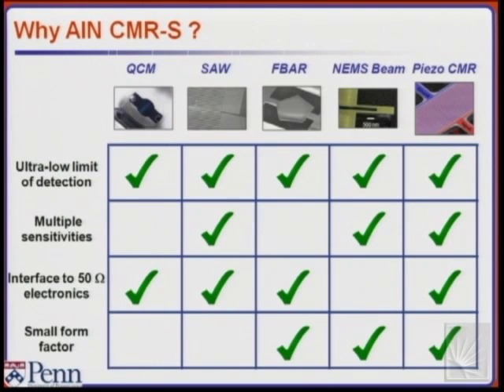So in making multiple devices on the same chip in a small form factor, that will solve the problem of selectivity substantially. That is the key problem of a sensor. You can't make an array of quartz crystals. It will be as big as this desk if you make 1,000 of those devices, right? But you can make 1,000 of these devices and still fit them in a centimeter square. And that, I think, is really going to solve the problem of sensor arrays and making noses and so forth. So that's why we selected the Contour-Mode Resonator as the key solution, because it embeds all those different characteristics over the other miniaturizable solutions that are out there.